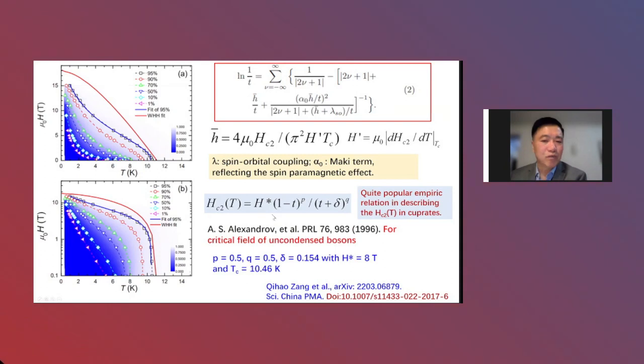So this 1 over 1 minus T is given by the dropping down of the superfluid density with temperature, and it gives the T power law in here. So here we assume a small delta. So we propose this kind of empirical law. We found that the data can be very nicely fitted by this empirical law, which suggests that we have uncondensed bosons, okay? Here are Cooper pairs, even above the upper critical field. This boundary just reflects the condensation temperature and field for the electron system, okay?